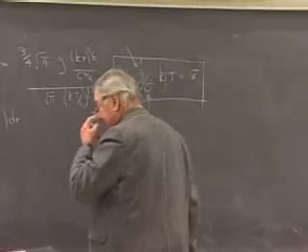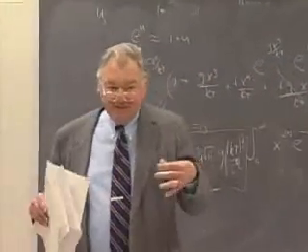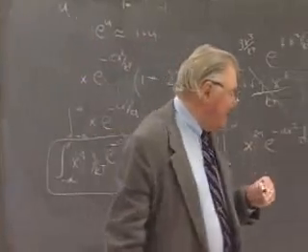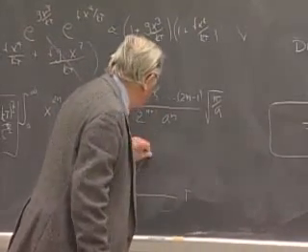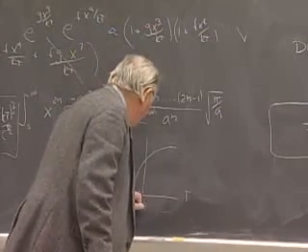Now, all this is true at elevated temperatures. At low temperatures, thermodynamics kicks in, and it turns out that the linear thermal expansion coefficient, as does the energy of vibrating atoms, must go to 0 as temperature approaches absolute 0. Okay? So a typical variation of the thermal expansion coefficient with temperature is something that does this. Same sort of variation as things like heat capacity, and this temperature in here is on the order of the Debye temperature of the particular material.